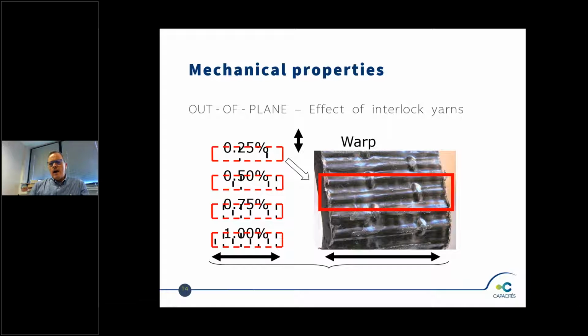And out of the plane, what we did was to try to understand how many interlock yarns we should have, which percentage of interlock yarns we should have in the part in order to optimize this weaving in a certain way. So we did a series of 4 specimens. The specimen with 1% interlock yarns has a series of yarns which were already woven in the material. And we played a game which was to remove some interlock yarns from the part and to manufacture the part after that in order to provide different ratios of out-of-plane yarns, just to check what was the influence of the number of yarns across the thickness of the specimen.